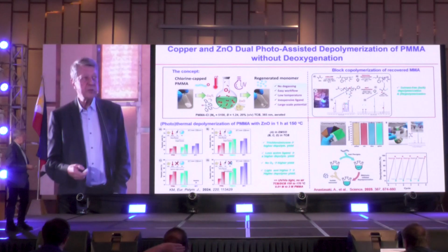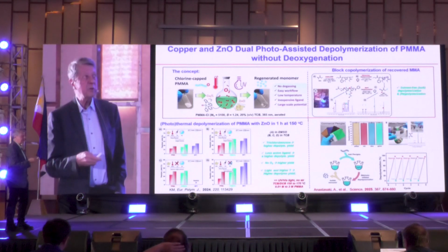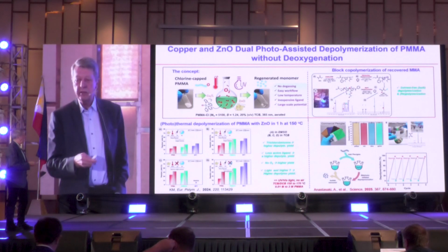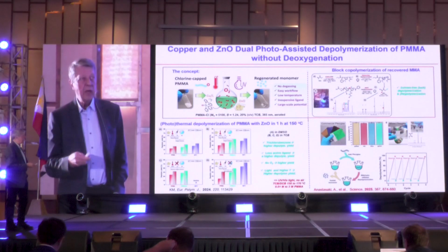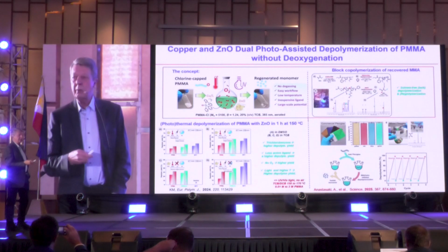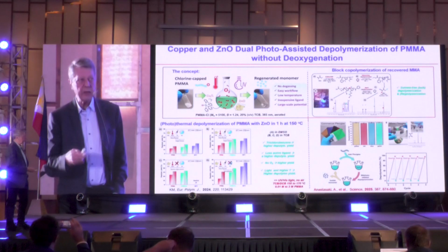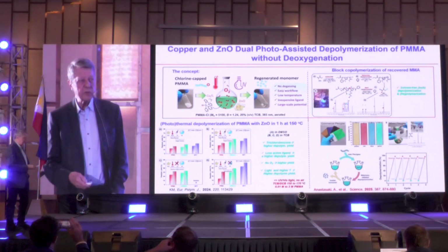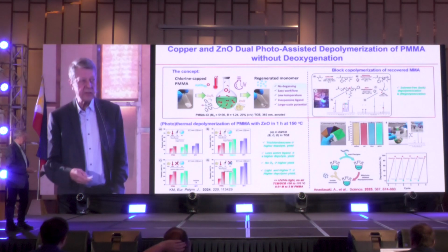Another possibility is shown here by using a combination of light and heat, and you can make methyl methacrylate or some other methacrylates. And very recently, a paper was published by Professor Anastasaki taking commercial polymethyl methacrylate with different colors. And you could see that you can regenerate methyl methacrylate with very high efficiency.